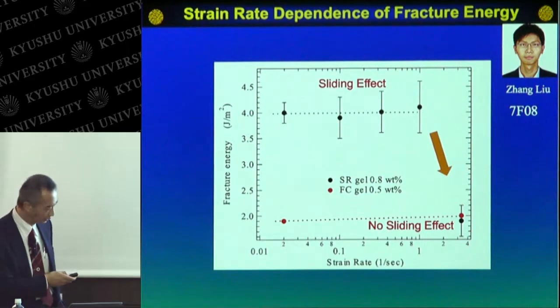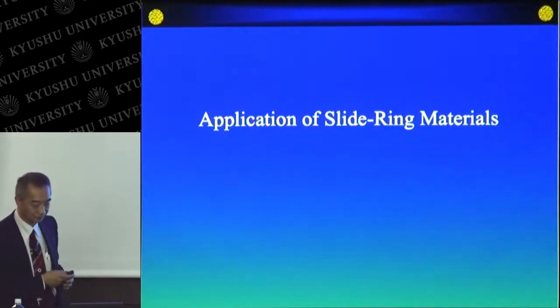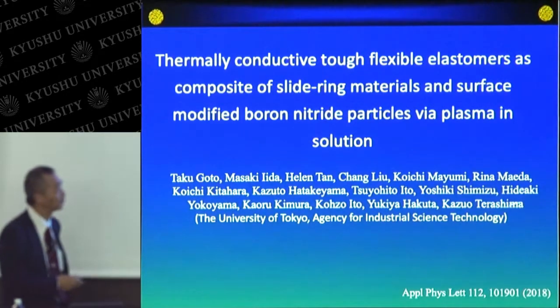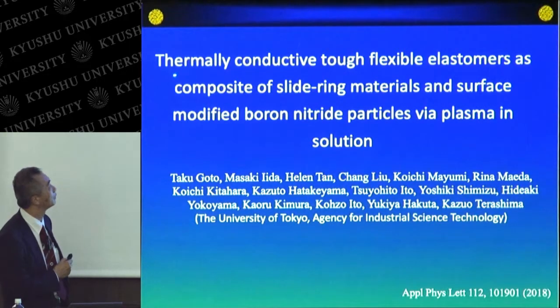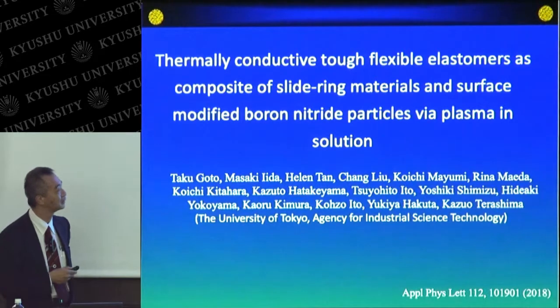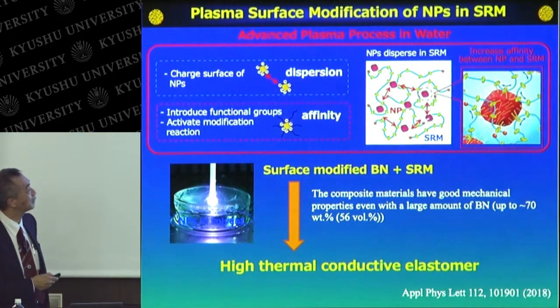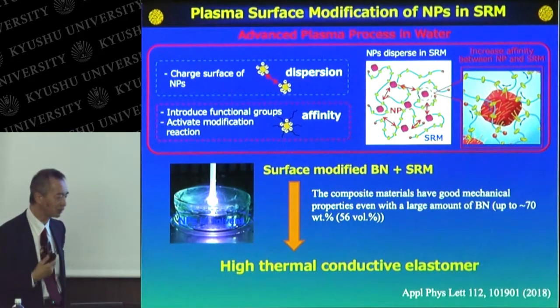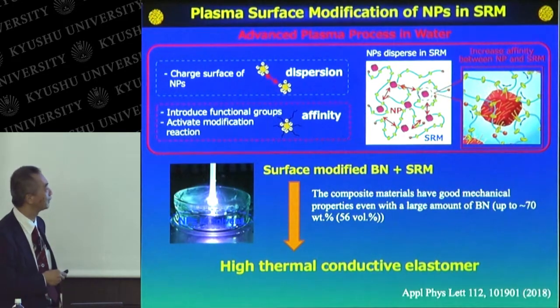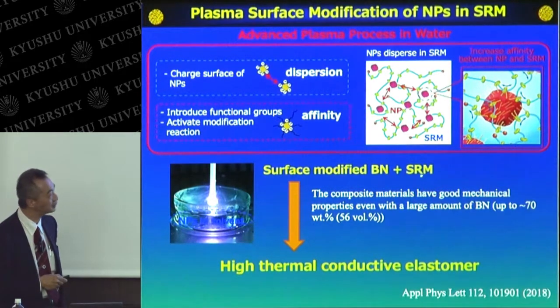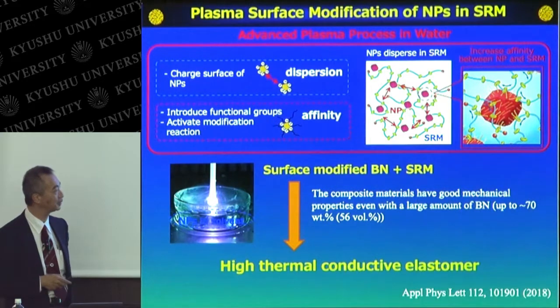Next, I'd like to show you some applications of sliding materials. Recently, we collaborated with Professor Terashima at the University of Tokyo to develop thermally conductive, tough, flexible elastomers as a composite of sliding materials and surface-modified boron nitride particles via plasma in solution. In this case, the surface of boron nitride is modified with the aqua plasma system developed by Professor Terashima at the University of Tokyo. We combined the surface-modified boron nitride with the sliding materials, and we achieved composite materials which have good mechanical properties even with a large amount of boron nitride, up to 70 weight percent.